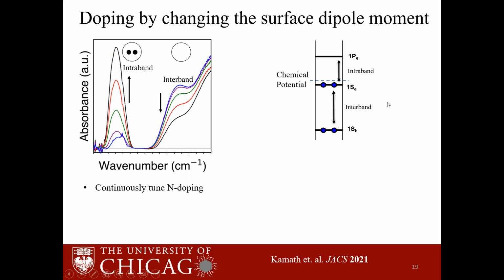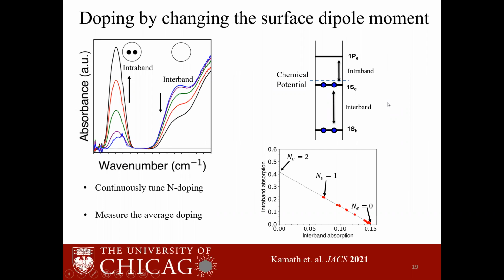While the initial quantum dots are undoped, which is seen by this blue curve, where we see almost no intraband absorption and a large interband absorption. As we increase the amount of cadmium acetate, we see that the intraband absorption increases and the interband absorption decreases. If we plot the value of intraband absorption versus interband absorption for all of these samples, we see this clear linear trend. And for any given unknown sample, if we put the position on this plot, this will tell us what is the value of doping of that sample.